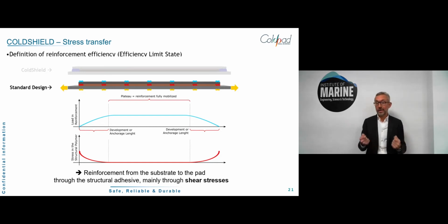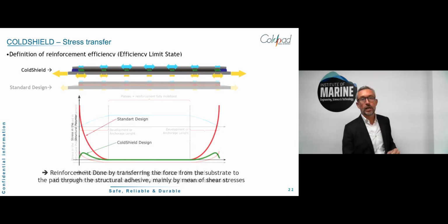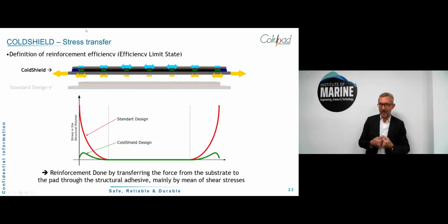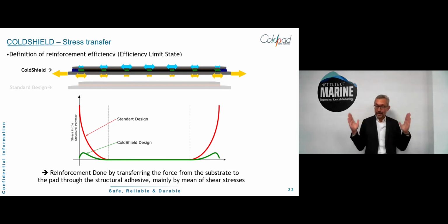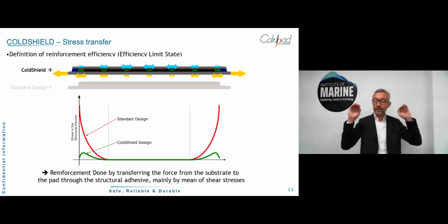Okay, and this is why the stress-based approach is actually a bit tricky when you are facing this. Usually, fracture mechanics is more appropriate. Right. So what we have added, because I'm a structural engineer, I'm used to stress-based approach. Fracture mechanics is a bit tricky and very difficult to actually control the order of magnitude. So what we have introduced here is this intermediate layer, which is an intermediate deformation layer that will deform sacrificially and that will reduce drastically this edge effect, so the stresses at the edge. And in that case, we have finite stress.